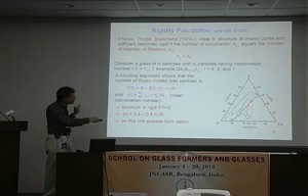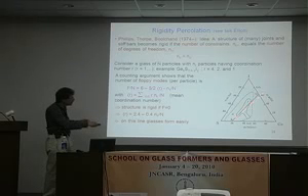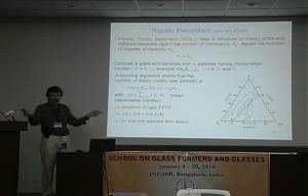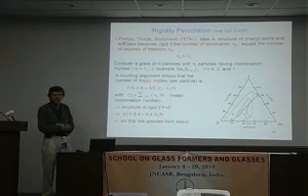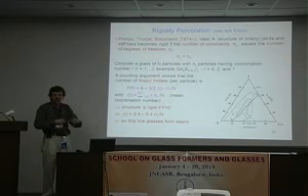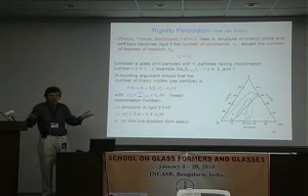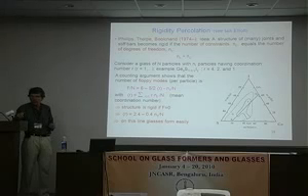And the observation is that the composition where you have good glass-forming ability is where the system is neither over-constrained nor under-constrained. That is to say, it coincides more or less with the line. So if you have too much frustration, it's not forming a good glass. If you do not have enough frustration or constraints, you're not getting a glass because it's not rigid. So that's basically the message. Okay.